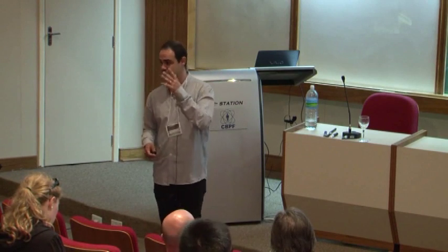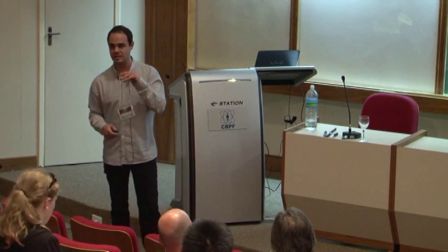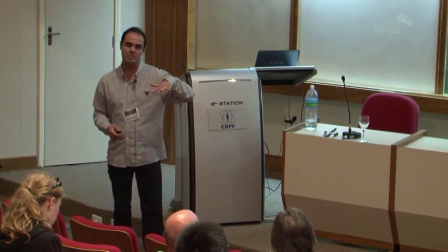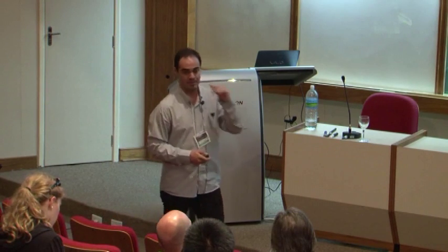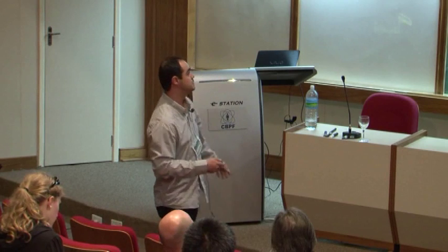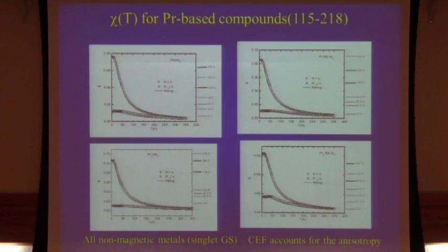So praseodymium can have a singlet ground state with no spin. So if it's a ground state, it will be non-magnetic, depending on J, if J is smaller than the splitting. But we can have a lot of features in the data that look like magnetic ordering or saturation just because of this level configuration. So one should be aware, when you're dealing with rare earths and seeing a lot of anomalies in your data, that they may have a very simple explanation sometimes.